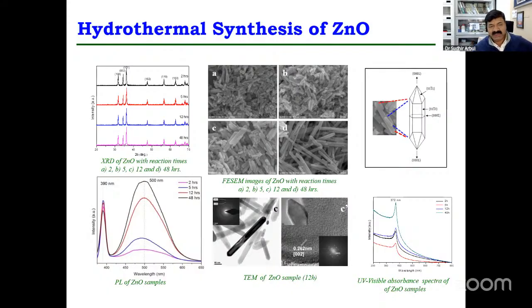To check its optical properties, using UV-visible spectroscopy, we got absorption at 372 nanometers. But in PL, what is happening? Zinc oxide band gap is around 3.2 electron volt. It is showing band edge emission. Band edge emission means what? This is the band gap. This is the valence band. This is the conduction band. The electron goes from this to this and again comes back here. It's called band edge emission.